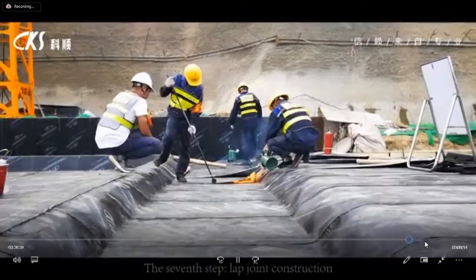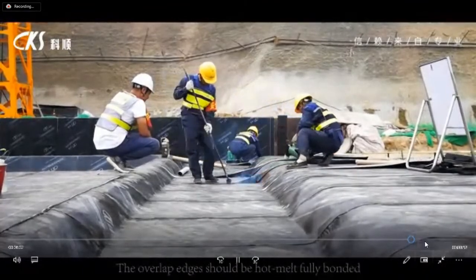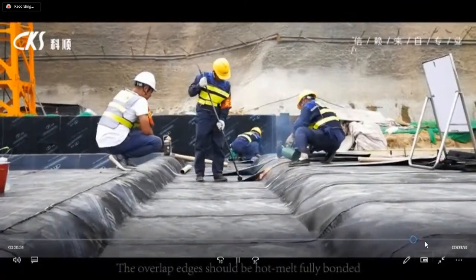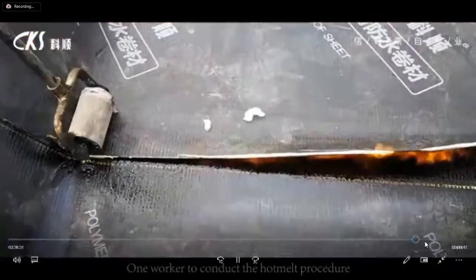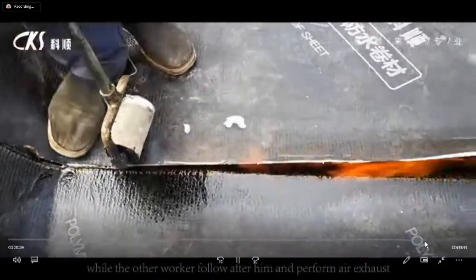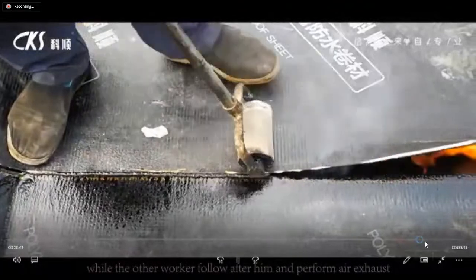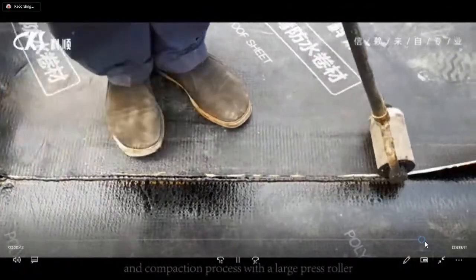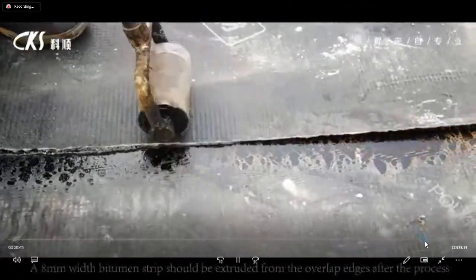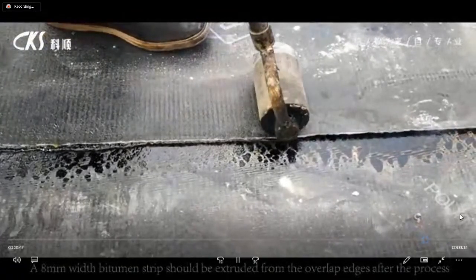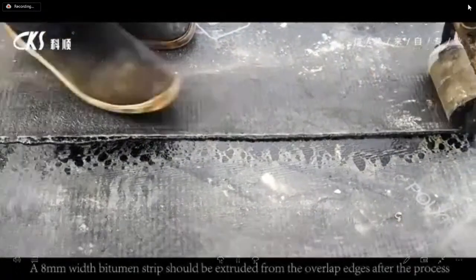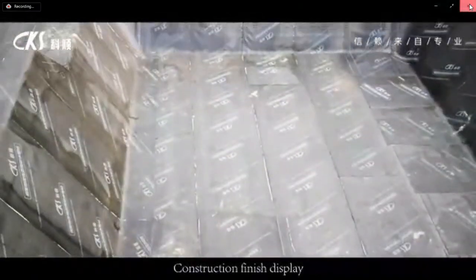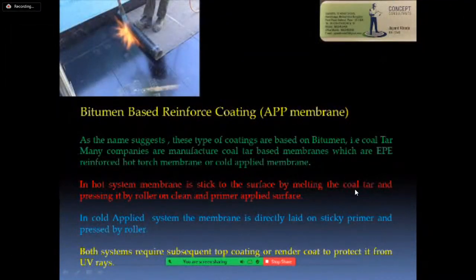The 7th step, lap joint construction. The overlap edges should be hot melt fully bonded. One worker conducts the hot melt procedure while the other worker follows after him and performs air exhaust and compression with a large press roller. An 8 mm wide bitumen strip should be extruded from the overlap edges after the process. So this is the method of bituminous membrane by torch-on membrane, hot torch.